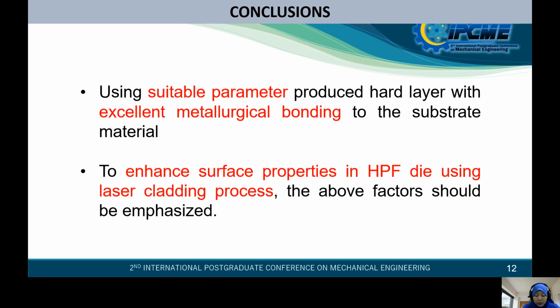And the conclusion, using suitable parameter produce hard layer with excellent metallurgical bonding to the substrate material and uniform composition and preferable coating thickness. To enhance surface integrity of the material, the above factors should be emphasized.